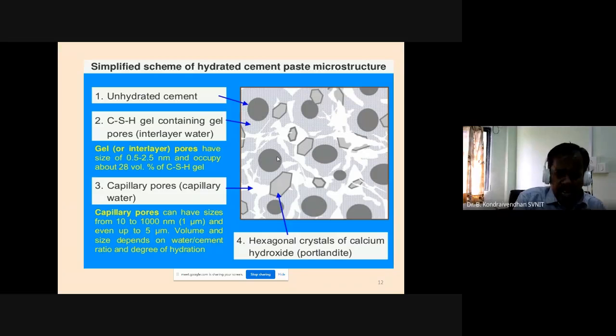And there are some big pores that are called capillary pores. Those pores are in the micrometer size range, which is why I also call capillary pores micropores. You can see the sizes varying from 10 nanometer to 1000 nanometer, and even up to 5 micrometer. Also, you can find some hexagonal crystals of calcium hydroxide.